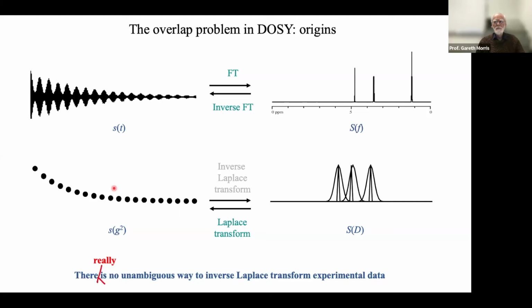And so one of the key things in designing experiments for DOSY analysis is that we prize chemical shift resolution. We prize the ability to resolve our signals in NMR dimension or NMR dimensions, plural, above almost everything else. Because if we can separate our signals and fit them to a mono exponential, we can get good information about the diffusion coefficient. But if we have overlapping signals, we're in trouble. So what happens if signals overlap?